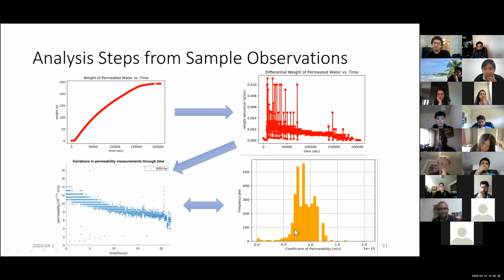This is a histogram basically to see which permeability is higher. And this we can do for every hour and every minute so that we can compute an average of permeability as the time passes from the sample. We can see that roughly it goes down as the test progresses.